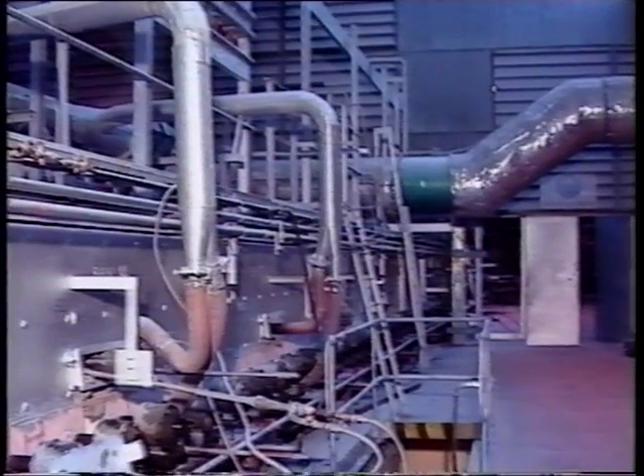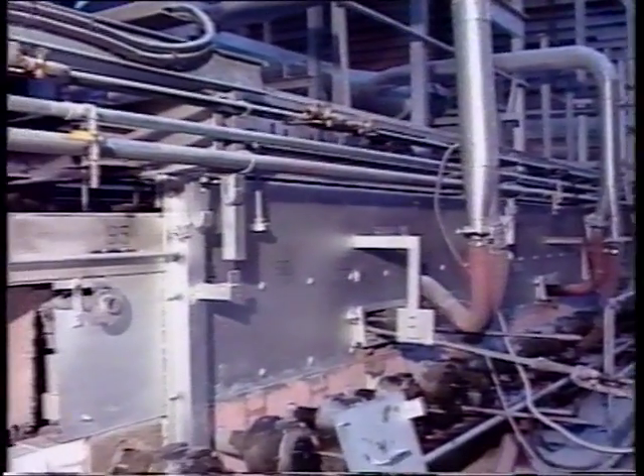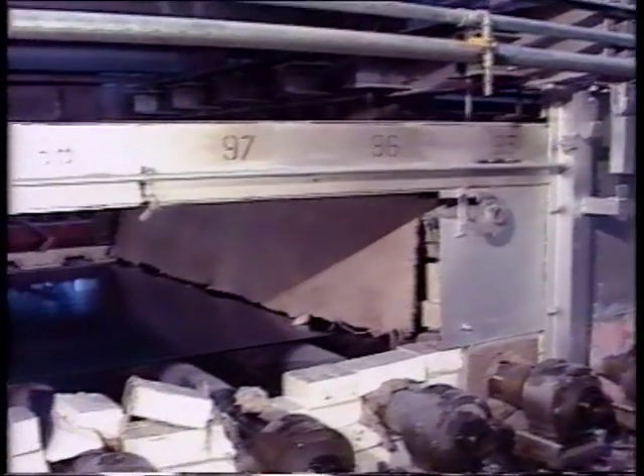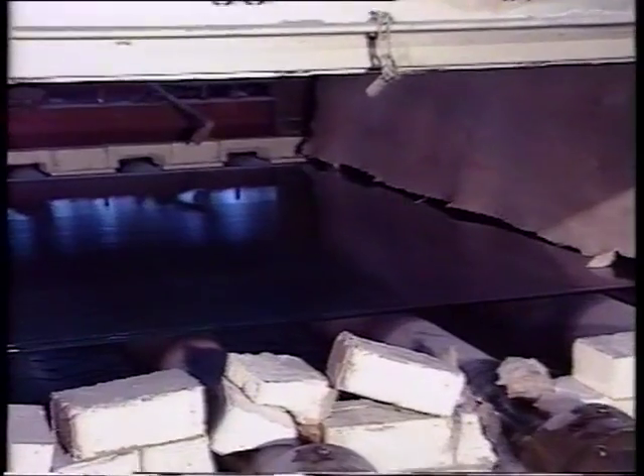A lot of work has also been carried out recently on improving the method of feeding the wire into the glass. This has involved upgrading wire feeding equipment to make sure the wire is fed straight and uniformly into the glass bolster system between the first and second pass rollers in the manufacturing operation. After forming, the glass is cooled in a leer under strictly controlled conditions so that glass stresses and shape after annealing conform with strict specifications for the Doncaster grinding and polishing operation.